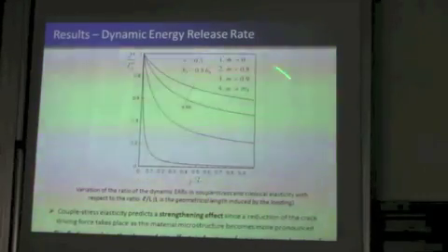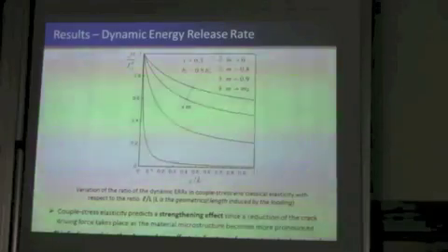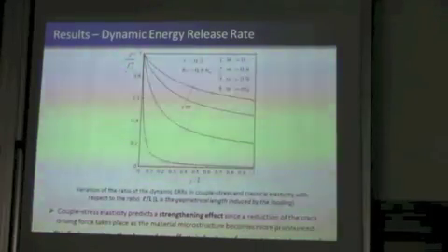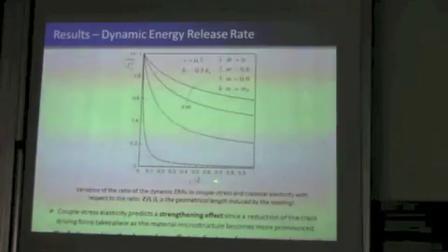And this finding actually explains the first graph that we saw in the beginning about the cracked ceramic and about how the energy release rate decreases when the flaw size of the crack in the ceramic material is comparable to the grain size. So this shows analytically how this happens when these become comparable.